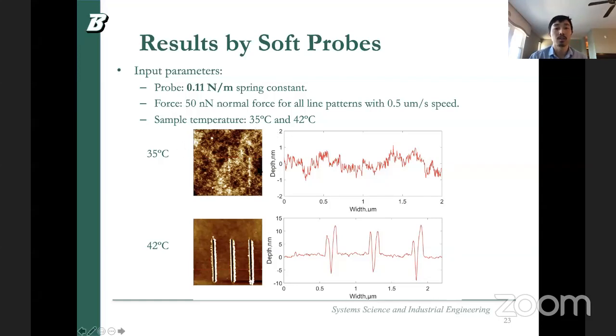So let's see the results. If you're using 35 degrees C and 42 degrees C, the temperature shows clearly that if we use a little bit higher temperature, with a very small force we can get trenches. If we don't use a little bit higher temperature, we cannot get these trenches. As you can see, at 35 degrees C we can only get a few marks on the surface. It's not even any trenches, not clear.